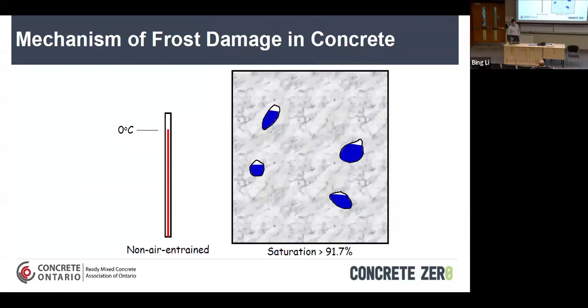Air entrainment for exposed concrete. So this is concrete. The reason why we have 91.7% saturation here, as you can see, is you don't have the voids fully filled. The concrete temperature is getting down, or let's call it the water temperature is getting down to 0 degrees. What happens? Water starts to freeze. You get even colder because there's a little bit of salt in that water actually, so you have to go usually lower below 0 degrees. Get a little colder. How did that happen? How did it grow? Because water expands when it starts to freeze. So that void is now fully filled with water and ice.